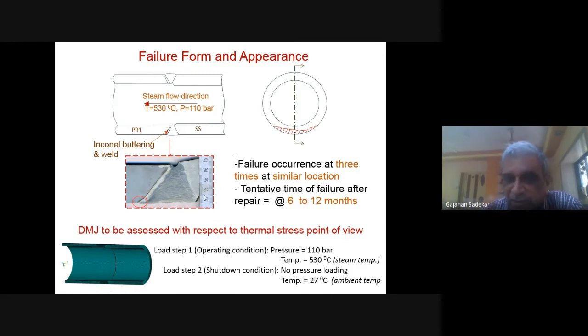So when this case came to us, fortunately we could get one of the samples, the complete failed sample of that particular portion, because it was occurring many times. They repaired it three or four times, then they replaced it with a new pipe. So they said, okay, we'll give you the sample which is available, and they gave us the sample. Then we did a detailed analysis of it.